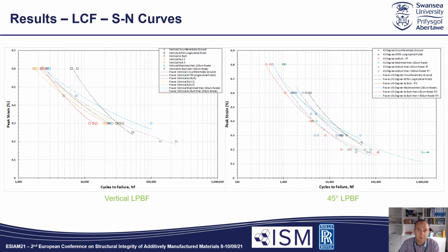Looking at some of the LCF results now, so given here are the SN curves for the vertically built and 45-degree samples. As you can see for the vertically built specimens, given in the graph to the left, as expected, the as-built and deliberately machined specimens offer the worst LCF response, with the mass finishing vibratory procedures and the ASTM longitudinal finishes offering the best response at the lower and higher applied strain levels respectively. Then for the 45-degree orientation, the graph to the right, again the as-built surface is the worst performing variant, with the ASTM longitudinal polish and the mass finishing procedures showing the best life. So it very much seems that surface finishes are having a direct influence on LCF performance, irrespective of the build orientation of the sample.